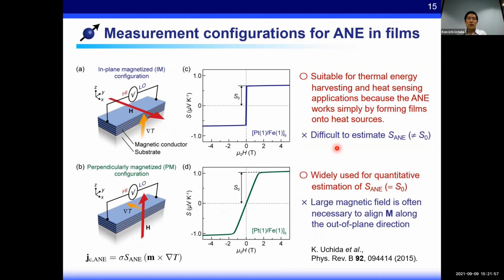In contrast, in the case of thin films, due to the huge difference in the thickness and in-plane dimensions, the measurement setups are classified into two categories. One is called the in-plane magnetized configuration, where the thin film is magnetized in the in-plane direction and the temperature gradient is applied in the normal direction of the film. This setup is suitable for energy harvesting because it works simply by attaching a film or sheet on the heat source. On the other hand, it's difficult to quantify the temperature difference between the upper and lower surfaces of the thin films. Therefore, the in-plane magnetized configuration is not suitable for the quantitative estimation of the anomalous Nernst coefficient.